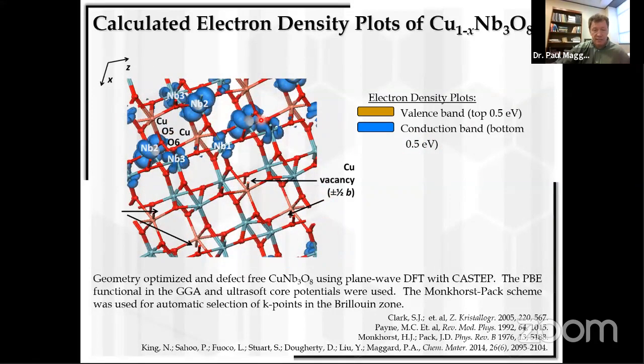When we introduce copper vacancies, the lowest part of that conduction band occurs up here. Wherever we have copper still present, that's the highest part of the valence band. And so there's this nice mechanism now of charge separation driven by the copper vacancies. And as you saw in the electron microscopy images, those copper vacancies are not just random. They're segregated. They occur mainly at the surfaces. And so there's a significant difference in the chemical composition of copper at the surface versus copper in the bulk that drives the charge separation at that electrolyte solid interface, which is really important.